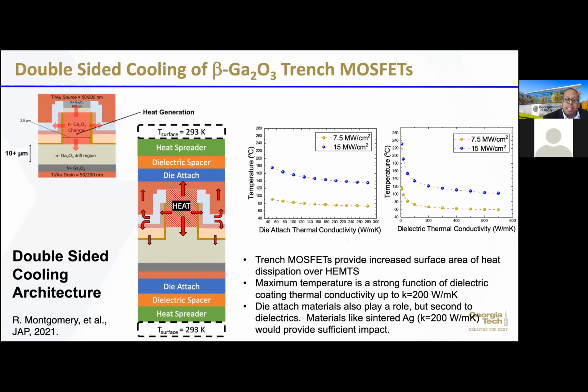The other one is, instead of using these lateral devices, to go to fins, so FinFET structures. We've seen this in silicon. And again, these die-attached materials are here for pulling heat out of the structure. The thermal conductivity does play a role at higher powers of these die-attached materials. But again, this dielectric material that you put inside of here, this is where you're going to see the biggest